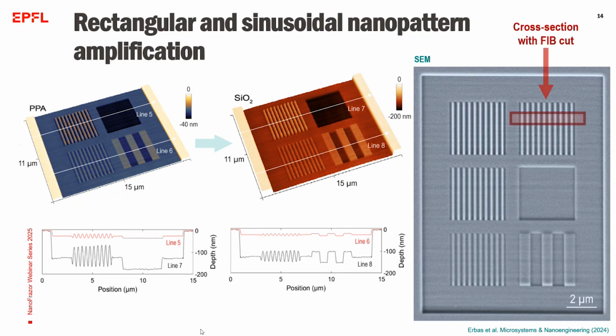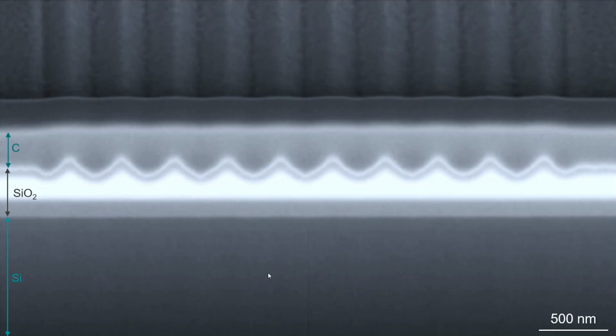And now let's have a cross-sectional view to better visualize what we have. So here you see a tilted cross-sectional SEM image, and the array of interest, grayscale SiO2, is first of all protected by a deposited carbon layer and then milled by focused ion beam. And in this specific case, sinusoidal nanopatterns in SiO2 with 400 nanometer pitch and 150 nanometer depth are fabricated free of shape distortion after 5 times depth amplification during the plasma dry etching.